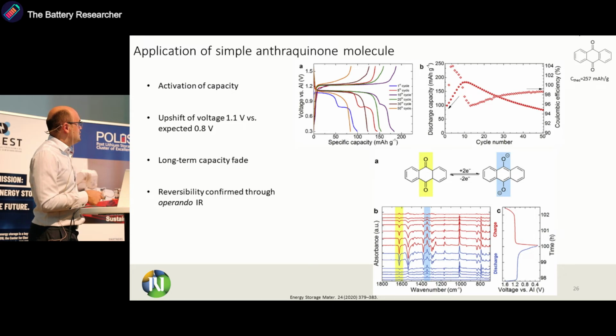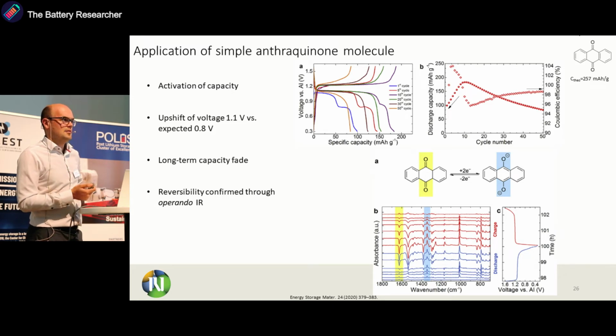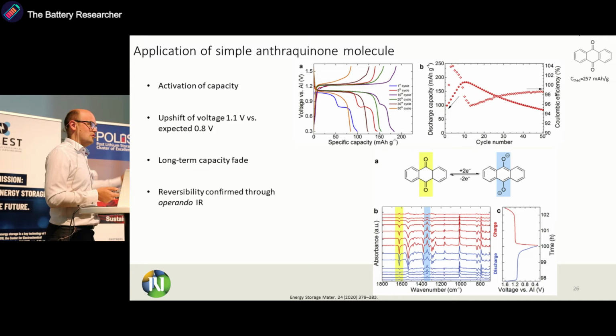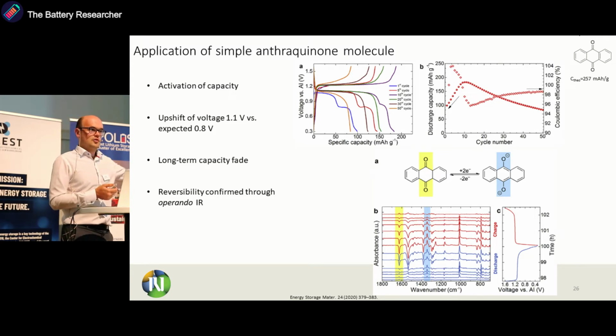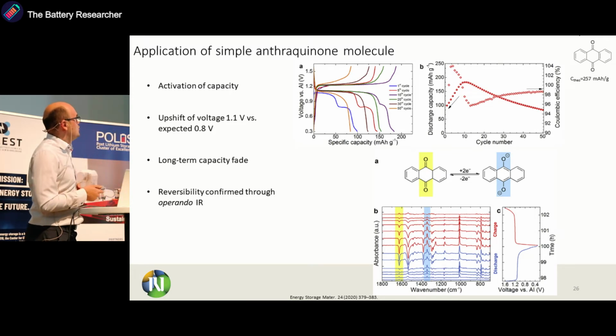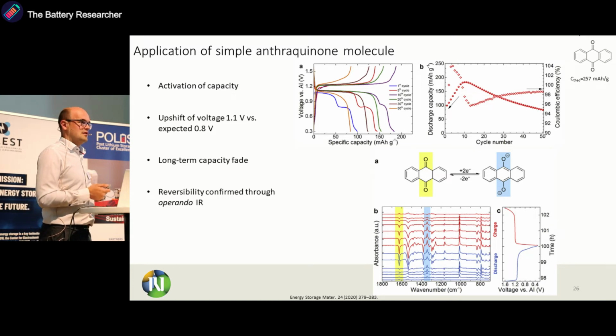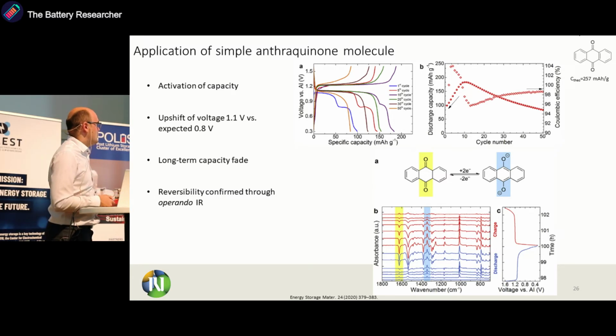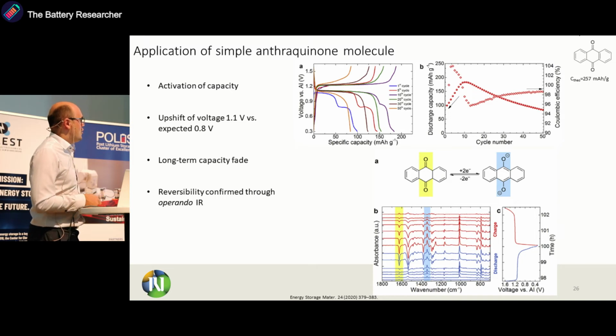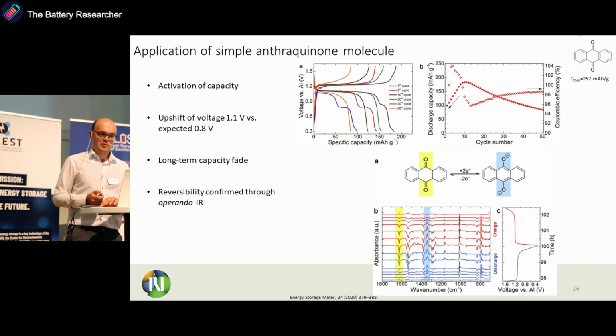And we saw that basically this 0.8 volt is what we would expect because the difference between lithium and aluminum is around 1.4 volt, and anthraquinone has 2.2 volts potential. But most likely, due to the fact that we have aluminum chloride in this system, we have basically upshift of the potential of an anthraquinone group. We confirmed this electrochemical mechanism also by Operando infrared, where we can see quite nicely that during discharge, we have decrease of intensity for this carbonyl band, and then this is going up during charge. So it means that performance is quite well reversible.